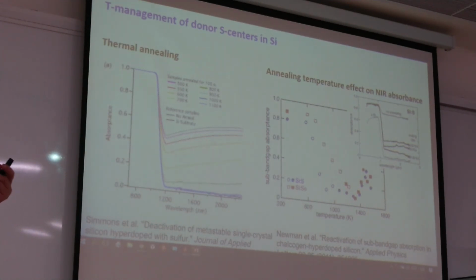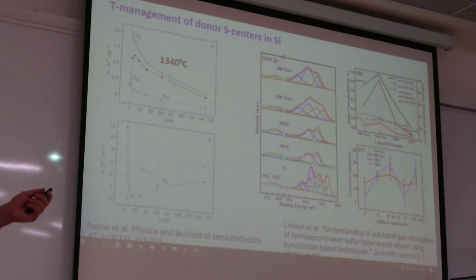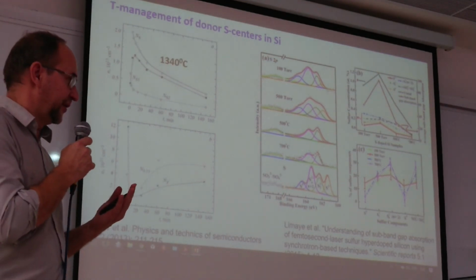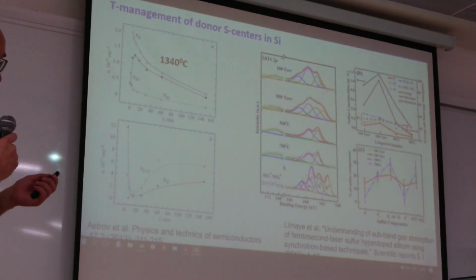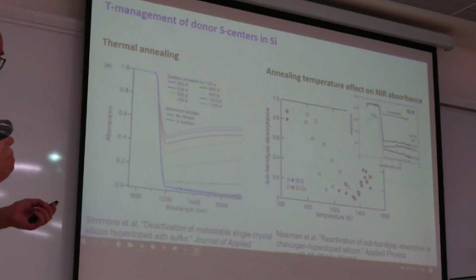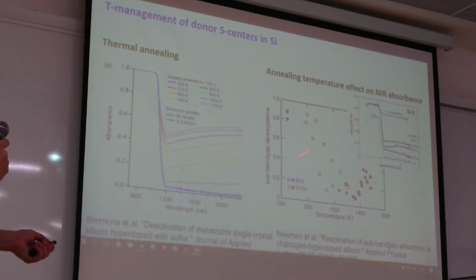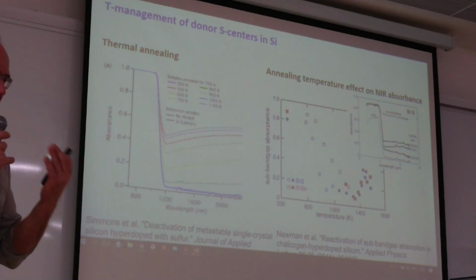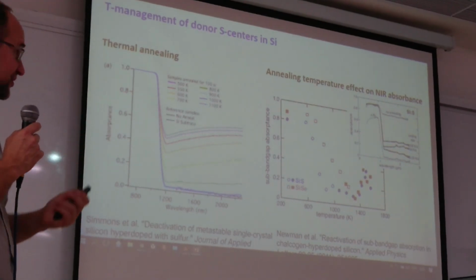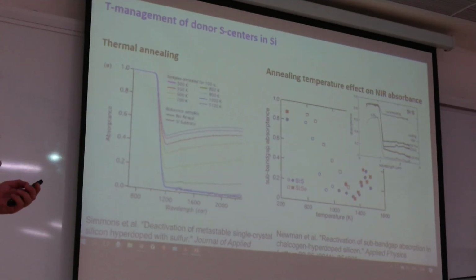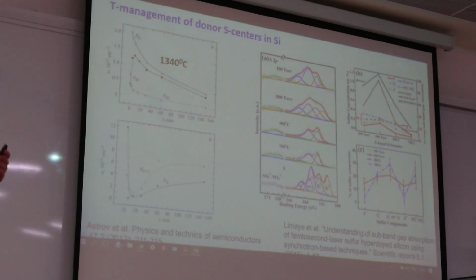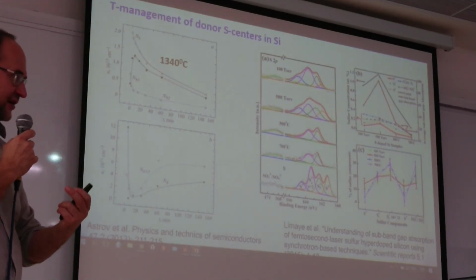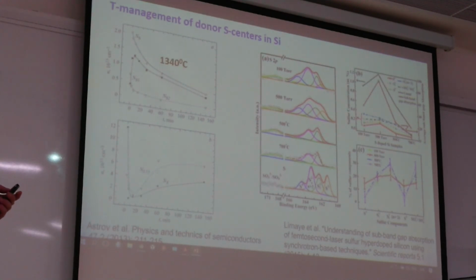And to understand why this happens and how people can use this, later people studied the chemistry of sulfur, because the absorption which was considered here and here in these experiments is the absorption of single sulfur atoms. But sulfur can make clusters, and clusters absorb further in the infrared region, and this could be even more important. So if you look at the chemistry of sulfur atoms inside silicon, we can use